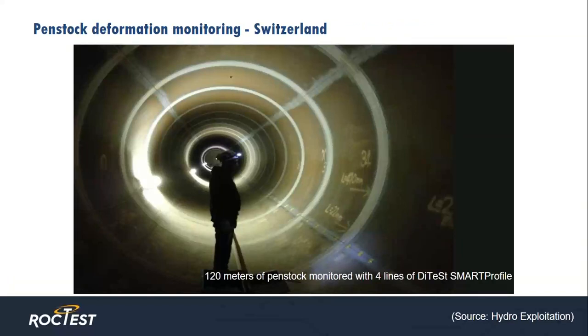The next project is a pump storage hydroelectric facility in Switzerland. In this instance, a penstock transports water from a collection reservoir down to the turbines at the power station. During a scheduled penstock inspection, a crack was detected in a section of the underground penstock. Subsequent inspections revealed not only were there cracks in the penstock, but also the welds in the steel penstock itself, none of them were 100% free of cracks.